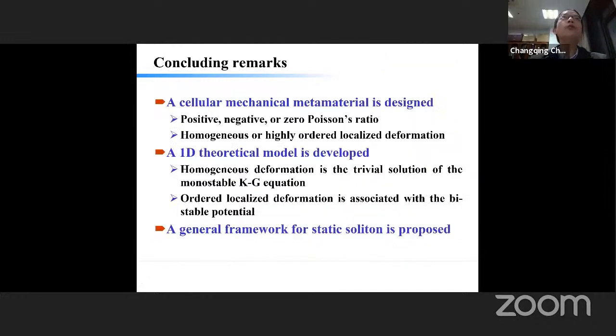So here comes the conclusion of my talk tonight. Basically, we used cellular mechanical metamaterials to show positive, negative, and zero Poisson's ratio. And we can have homogeneous and highly ordered localized deformation. Most importantly, we are interested in the highly localized deformation, showing up in the form of a static soliton, because we developed a one-dimensional theoretical model, which is a Klein-Gordon equation, and the solution in the form of uniform deformation corresponds to the trivial solution, and ordered localized deformation corresponds to the bistable potential.